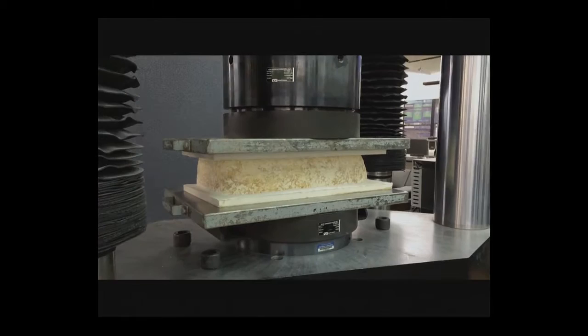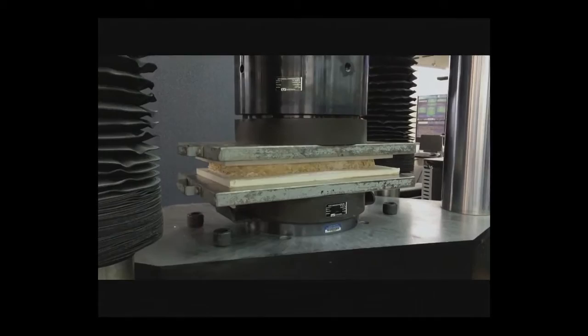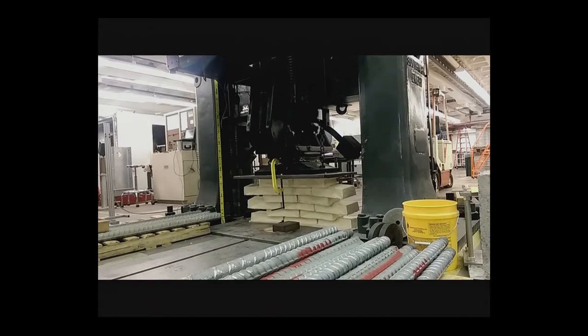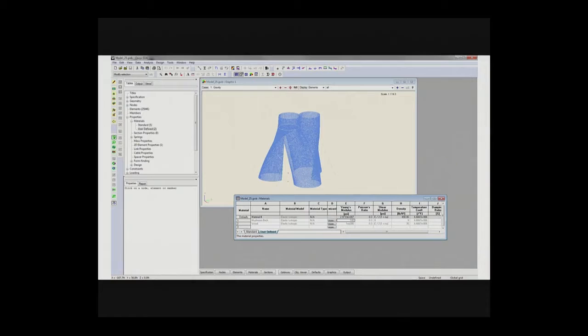Here's the brick we came up with. Since no one had created a large-scale outdoor application of this biomaterial before, we had to do a lot of testing. Here we're crushing one of our poor bricks under 100,000 pounds of force. We also crushed assemblies of bricks, because it was important to know how the bricks would behave individually and when assembled together. If you want to design a large-scale structure out of a new biomaterial, one of the first things you do is try to simulate it in software — but no structural engineering software on earth has a drop-down menu item for mushroom brick.